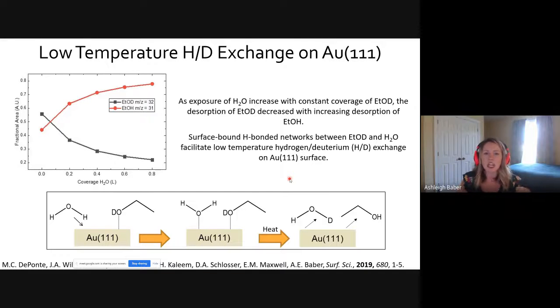What we found is that there's an exchange between the deuterium and the hydrogen on that ethanol on the gold 111 surface. So you can see here, if we look at the fractional area of ethanol versus deuterated ethanol, we start off with a lot of deuterated ethanol. And as we add more water, this is as a function of water coverage, we see that the amount of deuterated ethanol decreases, but ethanol increases. And so we're hypothesizing that there is some hydrogen-deuterium exchange occurring between these molecular species on gold 111, which is particularly surprising because gold is an inert surface. So it really tells you that the gold isn't doing anything except providing a space for these molecules to interact.